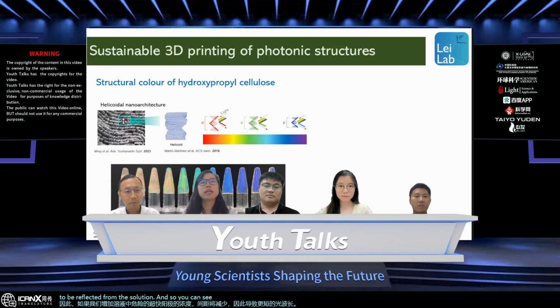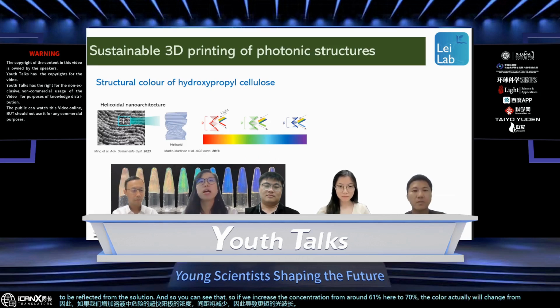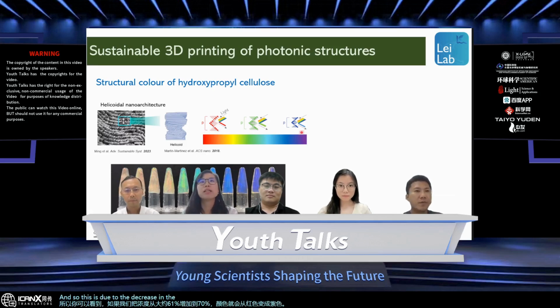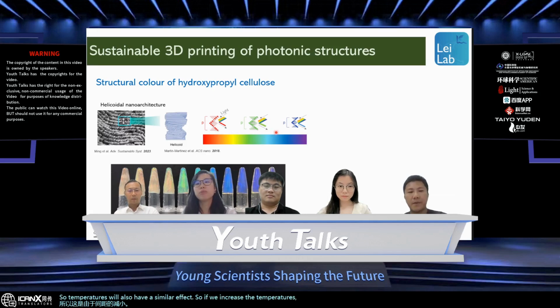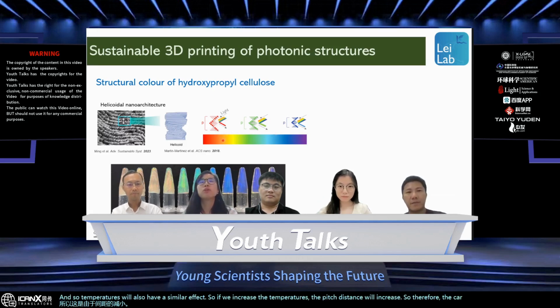So you can see that if we increase the concentration from around 61% to 70%, the color will change from red to purple. This is due to the decrease in the pitch distance. Temperature will also have a similar effect. If we increase the temperature, the pitch distance will increase, so the color will shift to a more red color.